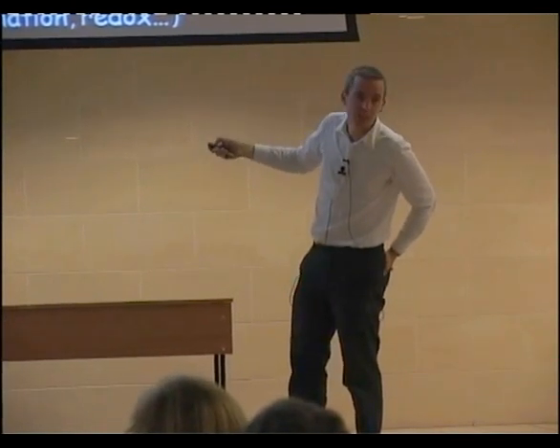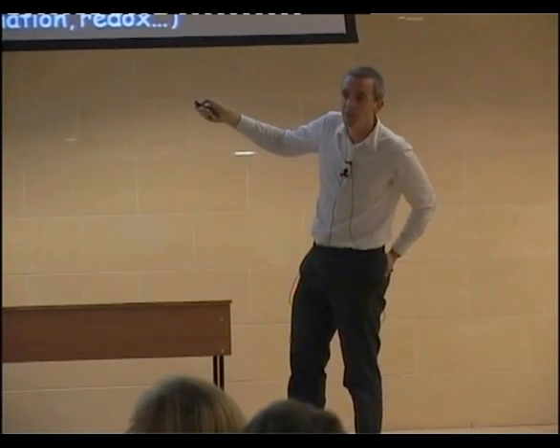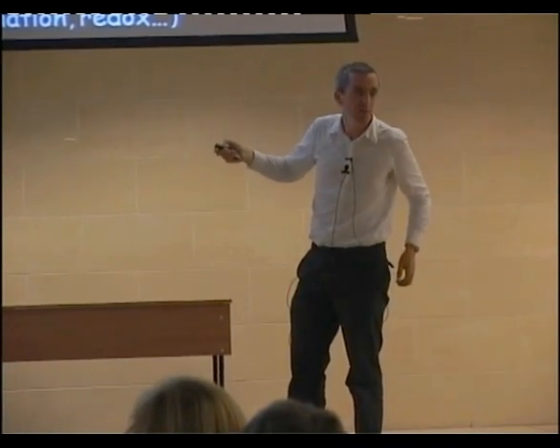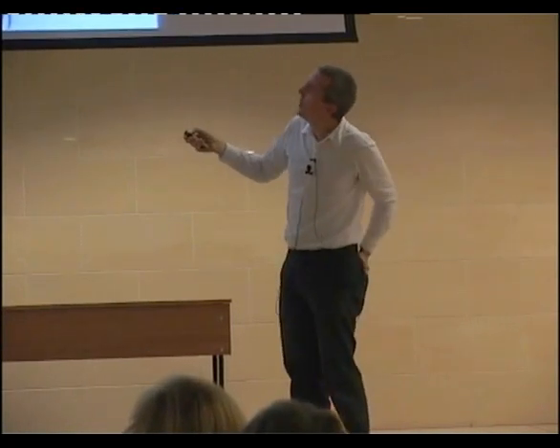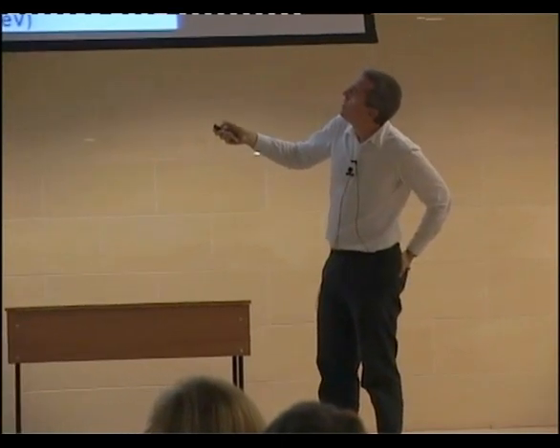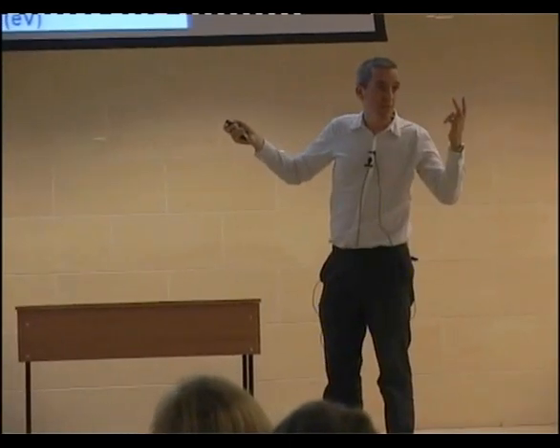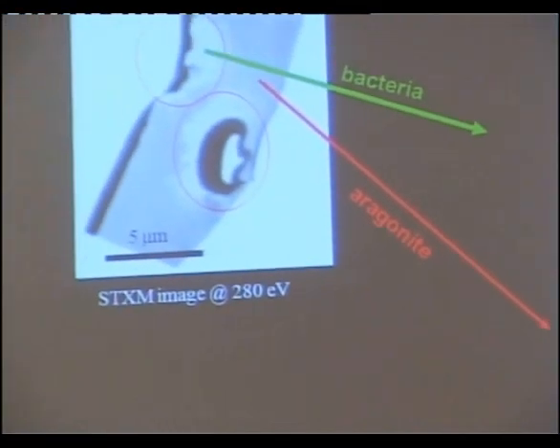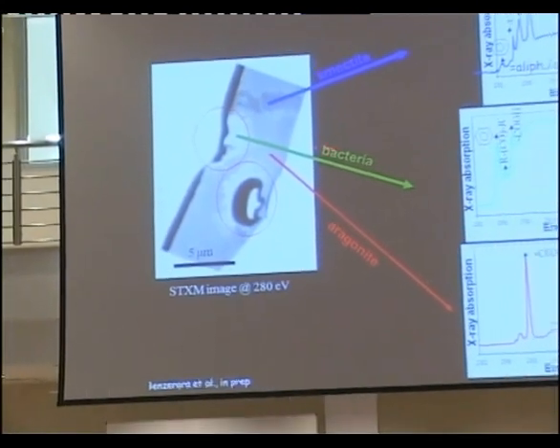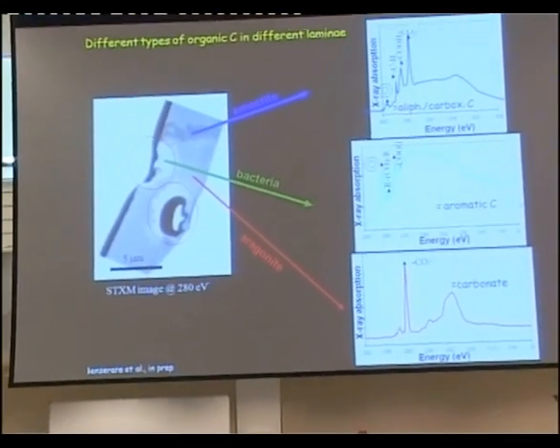Okay, that's the explanation. Actually, you look at electronic transition between orbitals and you probe the energy of the orbitals in carbon, for example. So that tells you something about the chemistry of carbon. So now if we do that for this cross-section, we find three different types of carbon. This one, this is typical of carbonate. So that's fine. This is aragonite, so this is carbonate, nothing new.